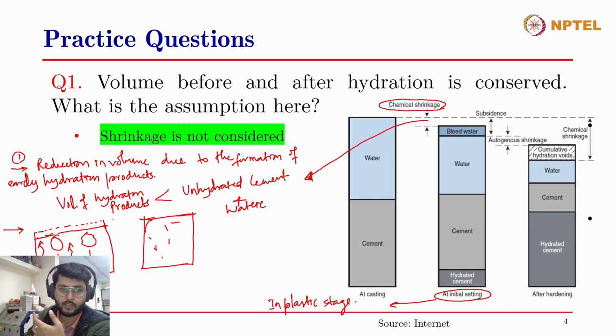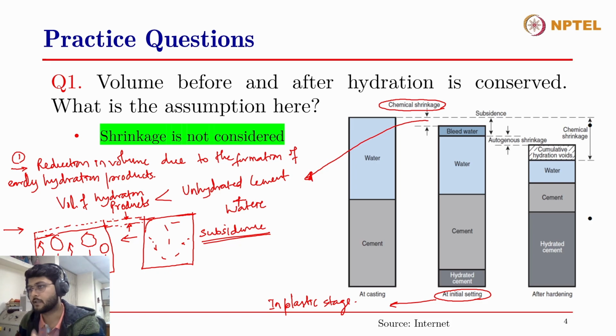When you cast a cube or something, initially the volume was the same, and this was a more or less homogeneous mix. But with time and due to segregation, the heavier particles have settled down, while the bleed water has accumulated on top, and therefore this difference in volume is called subsidence. That is, the concrete has now subsided or acquired a lower volume, while the top portion of it has been accumulated with water. So this is known as subsidence, as it is mentioned over here. This is the first one, the chemical shrinkage, and then, while it's just starting to set, this is the second one, subsidence.